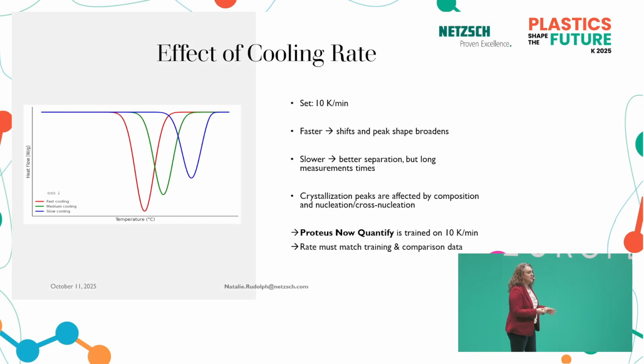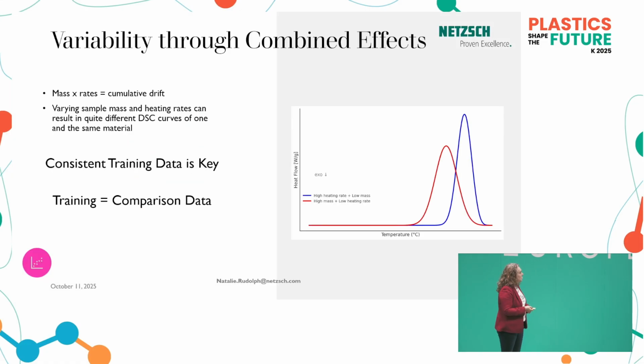Last, effect of cooling rate, similar to heating rate. This is also a schematic of how that would look. A faster heating shifts and the peak shape broadens. And so also for the cooling, we have defined 10 Kelvin per minute for the training data. And if you want to use Quantify, you have to upload 10 Kelvin per minute data. This is a combination graph that shows if I had mass and the heating and cooling rate mixed up, I could again get very different curves. And data training would be extremely difficult.